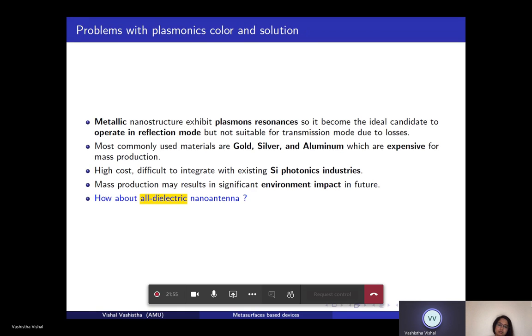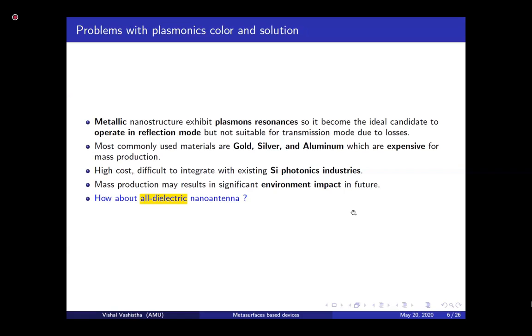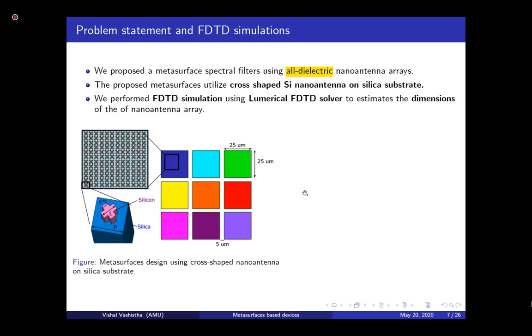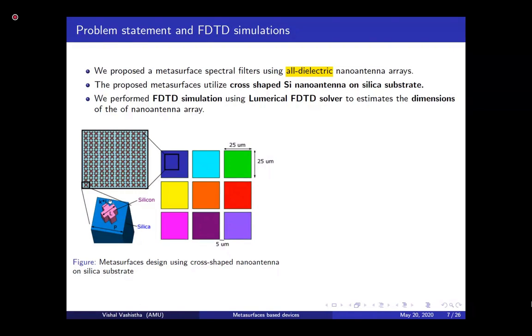We decided to make something using a natural material and an all-dielectric nano antenna approach to counter these losses. Here is our approach: we decided to make an all-dielectric nano antenna array. The unit cell consists of a silica substrate — basically glass — with a silicon cross-shaped nano antenna on top. Silicon behaves like a dielectric in the optical frequency range, so it's almost a lossless device. We fill this cross-shaped nano antenna across the whole surface — this is our metasurface.